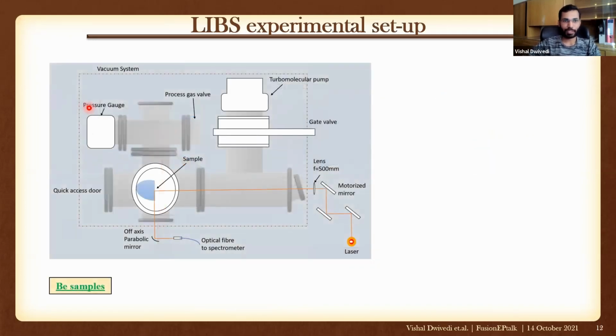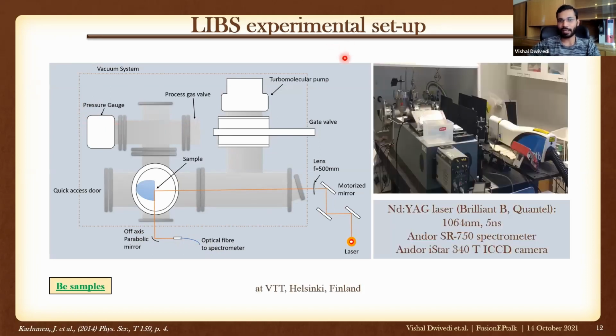For beryllium samples, we don't have permission to work in Slovakia, so we measured at VTT Helsinki, and this is the experimental setup from there, and it's quite similar. We can see laser, some optical components, mirror, and the lens. The laser beam is focused on the sample inside the vacuum chamber, and collection is done by parabolic mirror and optical fiber to the spectrometer, and all other components are related to the vacuum system and adjusting the pressure and background gas.